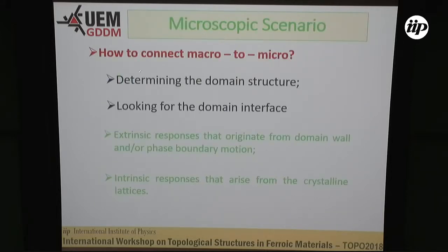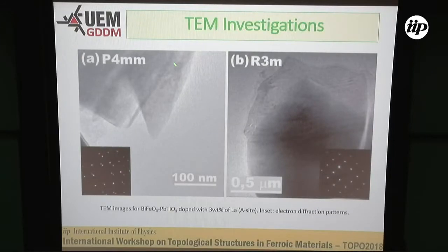We try to connect macro properties to micro characteristics of our sample, determining the domain structure and looking for the domain interface: the extrinsic response that originates from domain wall or phase boundary motion, and the intrinsic response that arises from the crystalline lattice or the thermodynamic stability of the system. We did some transmission electron microscopy characterizations in this sample that has 3% of lanthanum. Why this sample? Because in this sample we have tetragonal and rhombohedral phases coexisting in the same material.